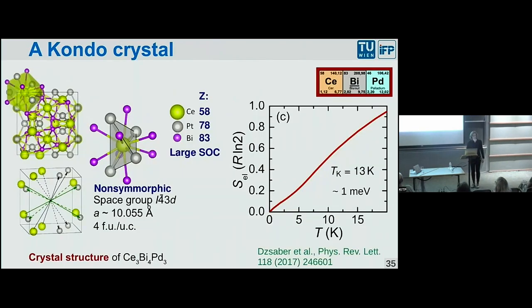And then we also choose the right symmetry. I told you the symmetry is very important. So we choose a so-called non-symmorphic symmetry, which is also non-centrosymmetric. So it has this screw axis, which is here, the four minus is again such a fourfold screw axis. So it has the right symmetry elements so that this non-canceling effect of the Berry curvature can exist. And we can measure properties that tell us that, yes, indeed, this is a very strongly correlated material.